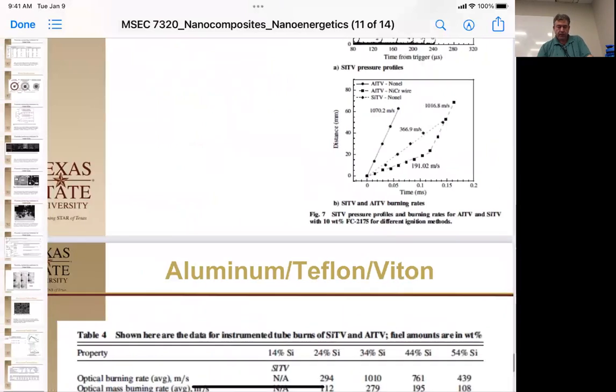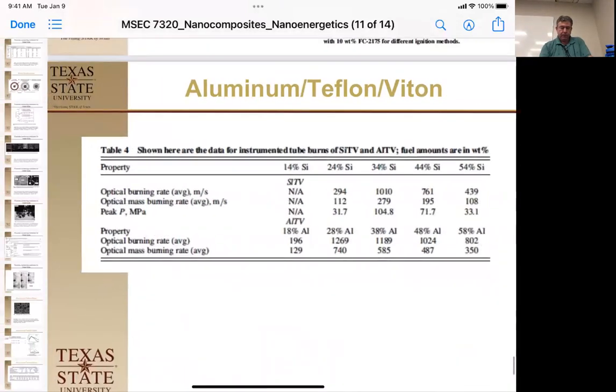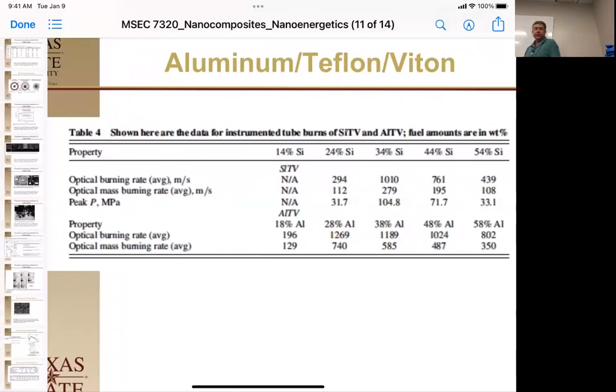Okay. All right. So then what they did was they analyzed it by their different amounts of the metals in there. Then they looked at an optical burn rate, which was done with a high-speed camera, and then the optical mass burning rate. So that's also kind of like by looking at the pellet diminish. And then they looked at their peak pressure. And so when we see here, the 24 was about where we were looking at pretty good. And it's about 300 meters per second, 1,000 meters per second, and then it starts dropping off again.